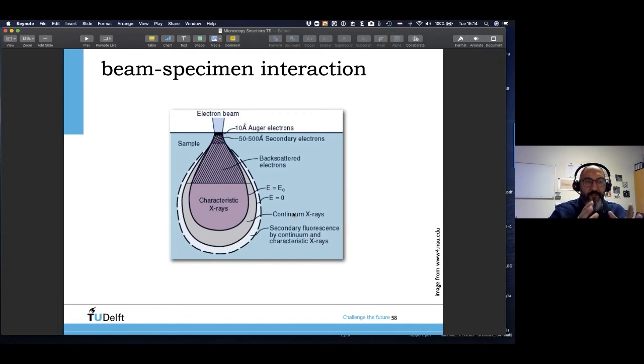So is this something fixed, and you always have the same volume? No. As an operator, it's up to you to define at what speed, figuratively speaking, you are sending your electrons on top of your surface. You can increase your accelerating voltage from, I don't know, 5 kilovolts to 10 to even up to 30 in typical systems. And the higher the accelerating voltage, the larger the interaction volume will be.